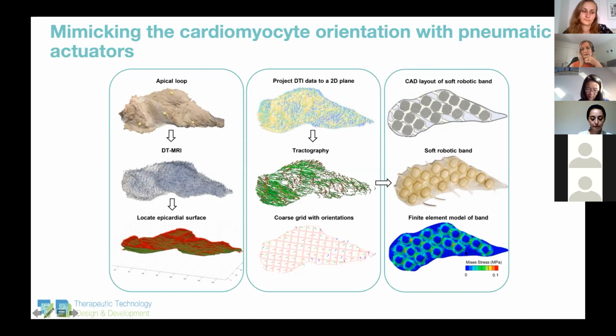And we can create finite element models to predict the stresses in those actuators, and also the strain, what kind of strain we'll see when we pressurize them. And we can characterize experimentally these actuators. The reason we went with these flat versions for this is that because we needed to wrap it and fit it back in the cardiac geometry, we didn't have a whole lot of real estate to place bulkier soft actuators.